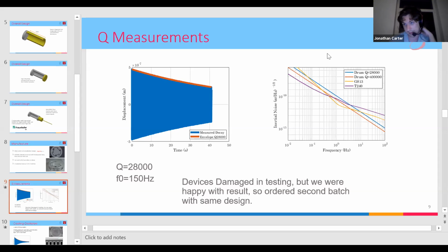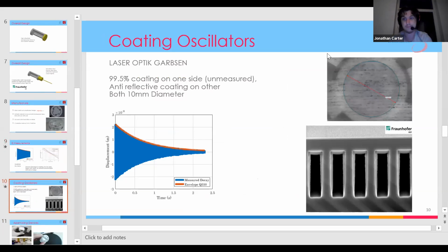Once we had these devices, it was a question of coating them, because to form the cavity, we needed a highly reflective mirror. We wanted to do this with layer deposition. So we contacted a local company in Hanover called Laser Optik Garbsen, and requested a 99.5% reflective coating on one side and an anti-reflective coating on the other. This was done in a 10mm disc in the center of the device to keep it away from the flexures, so that the material wouldn't dissolve into the oscillating parts.